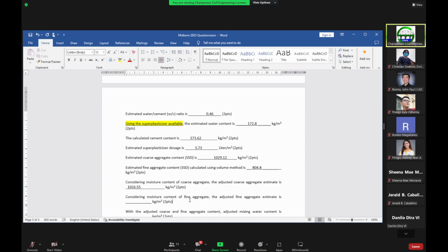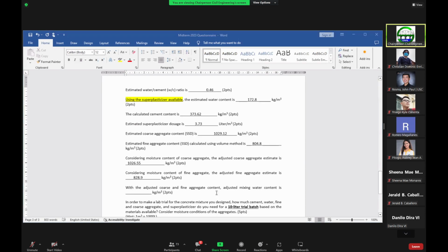Okay, that's your 804.8 plus the additional water that you need. So that's the 3% times 804.8. So you get fine aggregate estimate that's 828.94. Yeah. Okay. Next.